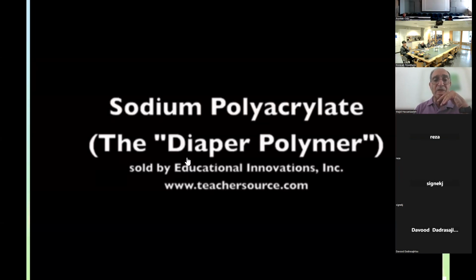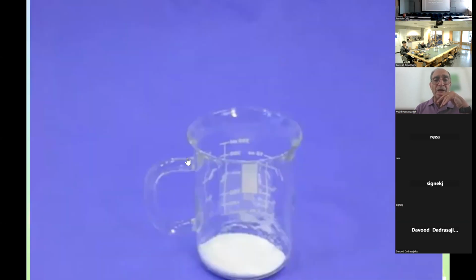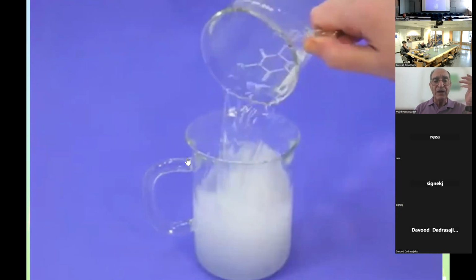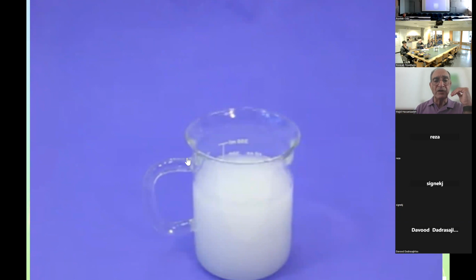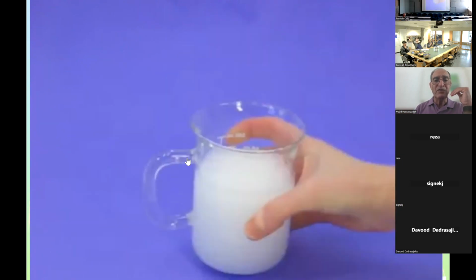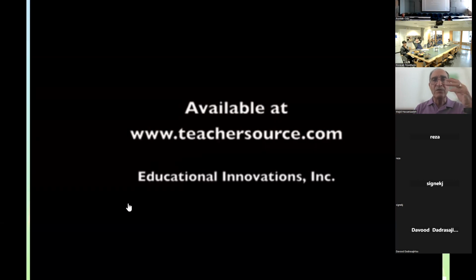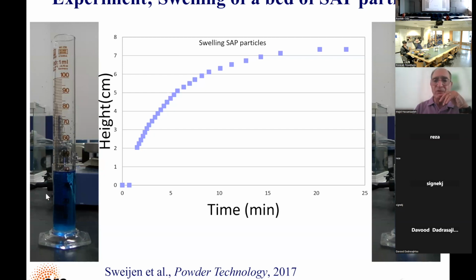You can see that also here, a nice experiment we have, where we have a layer of particles in there, and you see that it happens fast. The particles absorb, they grow, fill up the glass, and because they are pushing against each other, they won't come out. A similar experiment we did, though unfortunately the colors are not very good. On the left-hand side, we put a thin layer of these SAP particles in there. And on the right-hand side, it is completely swollen and filled up that whole liquid.